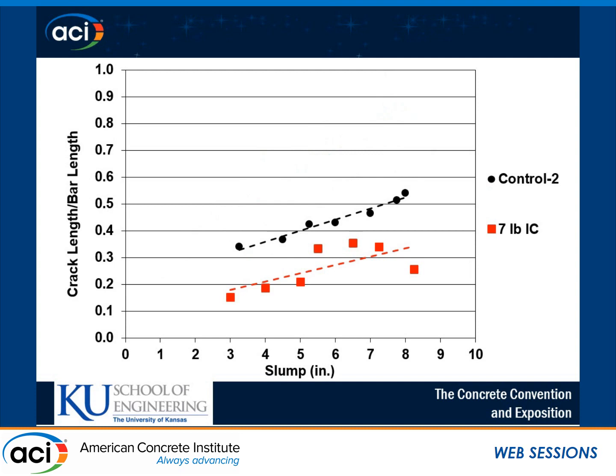So getting into our comparisons now, both of these mixes are 100% Portland cement, but the series in red has that partial replacement of lightweight aggregate pre-wetted to provide 7 pounds per hundredweight of IC water. And for each slump that we looked at, we did see a reduction in settlement cracking. The mechanism behind that is that the bleed water that's going to rise up in the system can be pulled out of those lightweight aggregate pores a lot easier than from the cement matrix. So the bleed water that comes out isn't being taken from the cement at all.